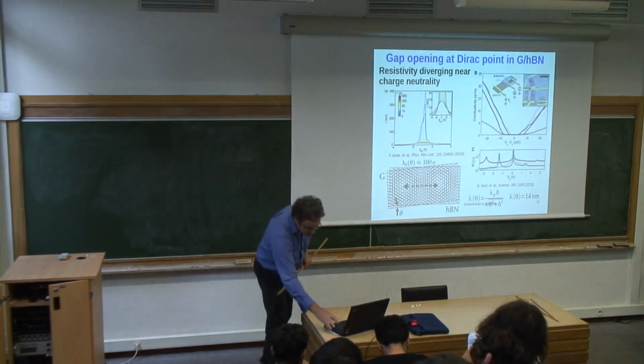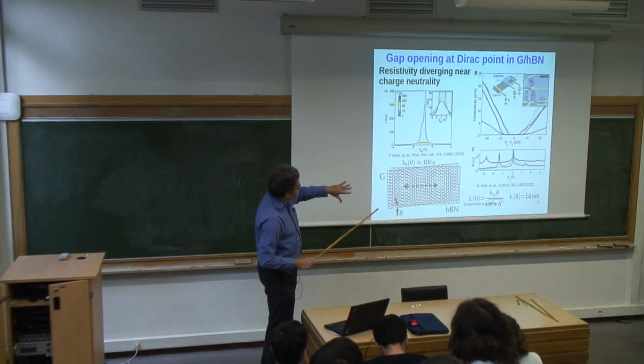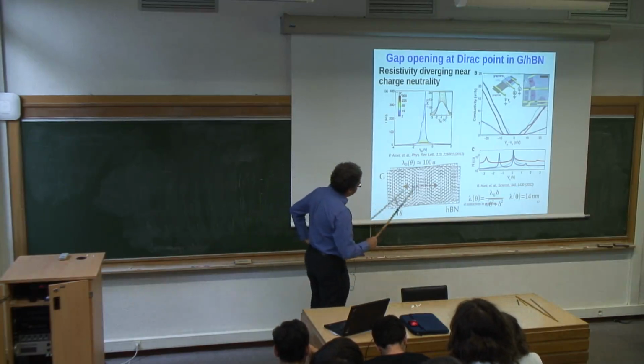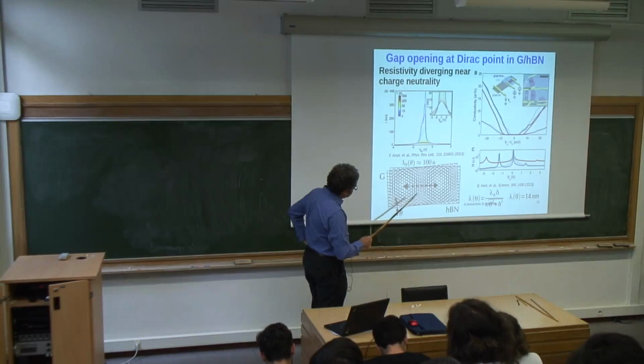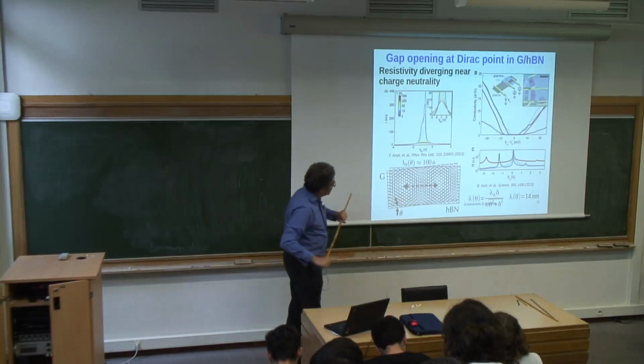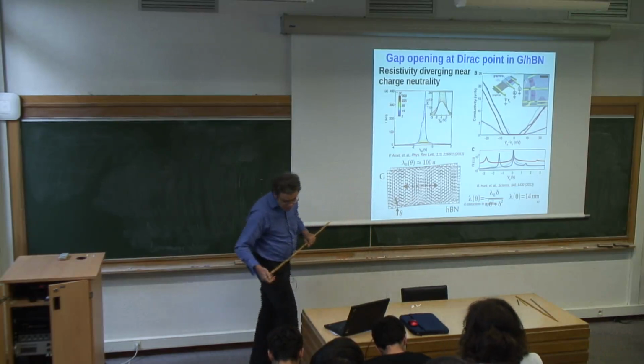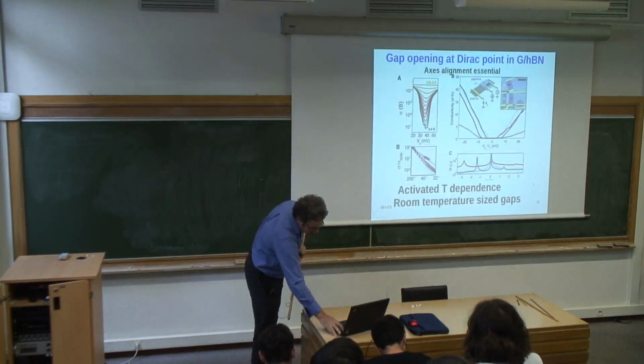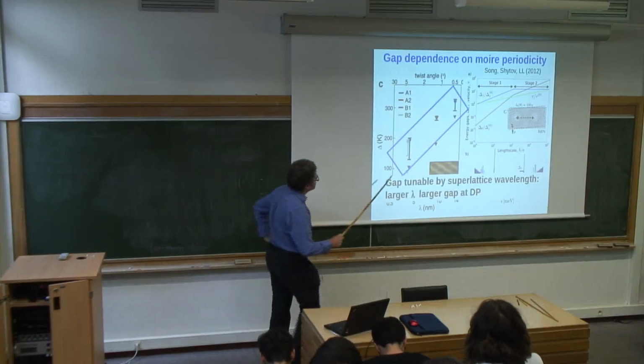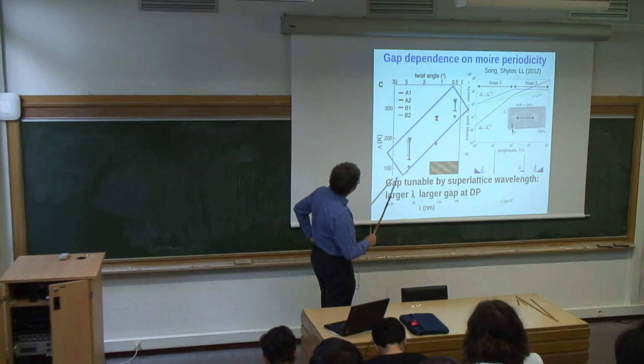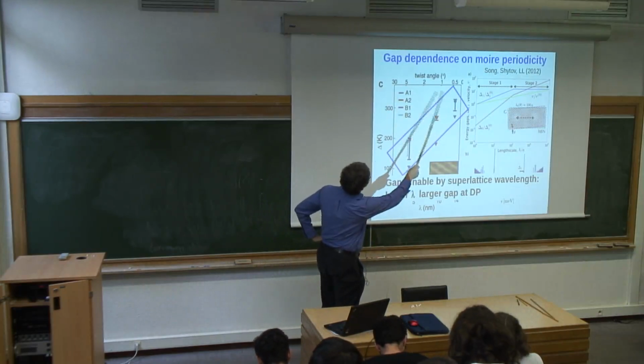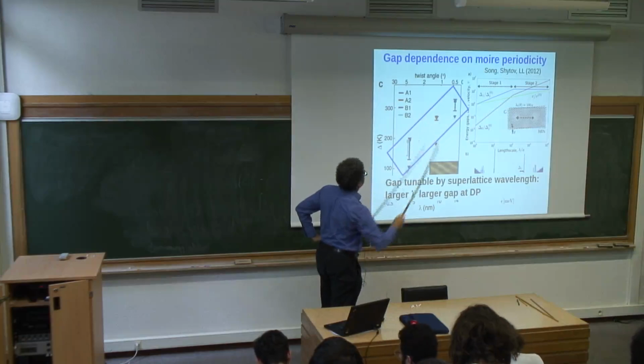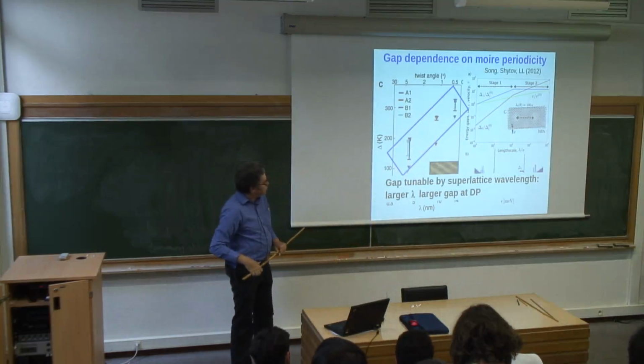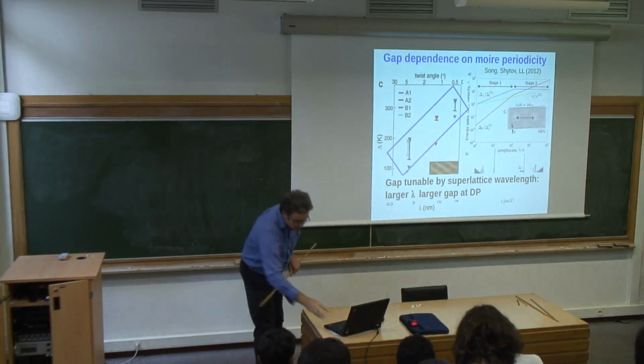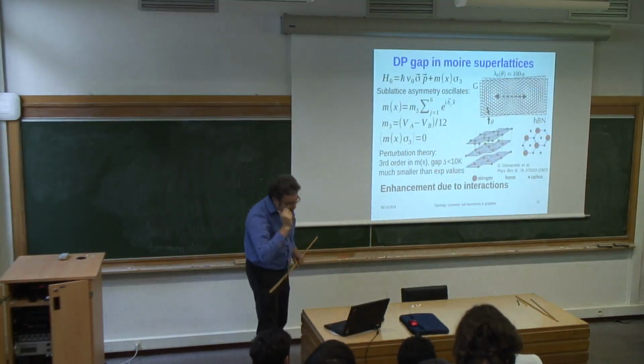So this is a quick review of what we said about experiments. When you place graphene on boron nitride with crystal axes nearly aligned, you find that there is a gap that you see from transport measurements, activation behavior, that depends on the angle between crystal axes, and you would like to understand this dependence. The dependence is such that increasing the angle suppresses the mass. Twist angle going down means gap going up, right? And so you would like to understand the scale, also this dependence, and you can do that by